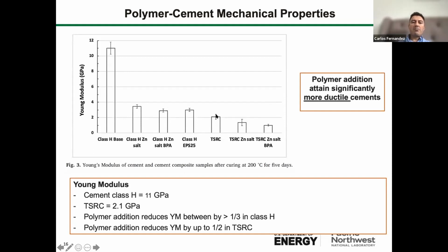And for thermal shock cement, which is a more ductile material than cement H with pozzolanic material, still the addition of the polymer reduces the Young's modulus by 30%, and in some cases halfway, 50%, which is again a very important feature of these materials. Why? Because we don't want a material that is brittle, because the fracture propagation rates are much faster, and what we want is a material that will reduce the fracture propagation rates and enable in that way self-healing or some autogenous healing by continued hydration, like in the case of materials that don't have self-healing but continue to heal just because there is still evolution of the hydration products over the years, days and months.